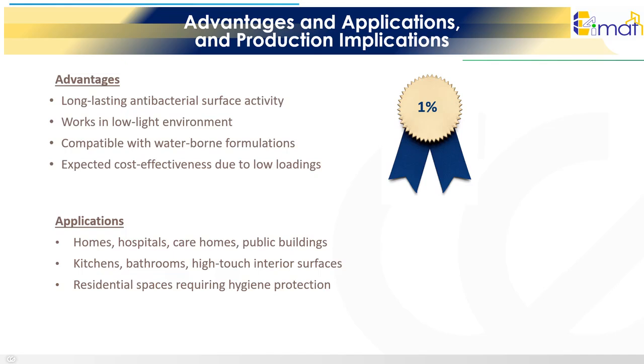Copper doping of titanium dioxide provides long-lasting antibacterial surface activity and works in low-light environments. The titanium dioxide dispersion is compatible with common water-based interior paint formulations. It is also expected to be cost-effective as minimal loadings are sufficient to obtain the targeted function.